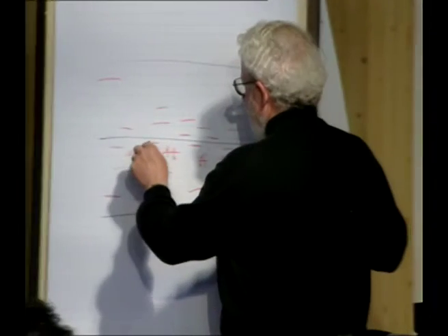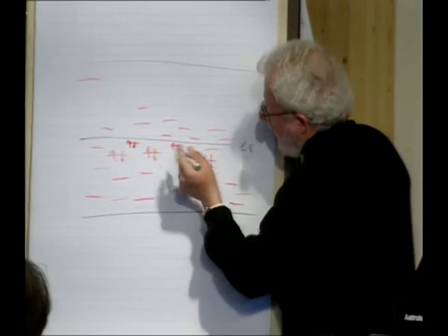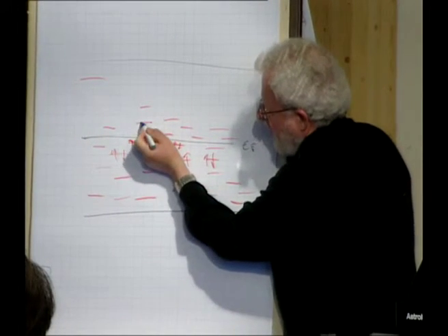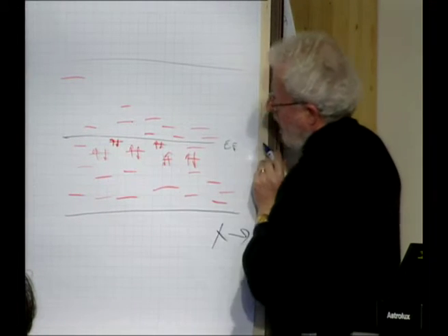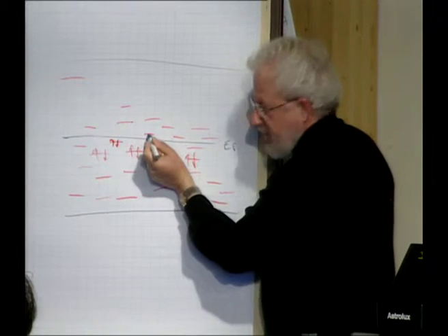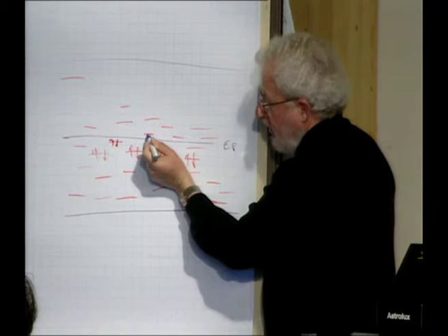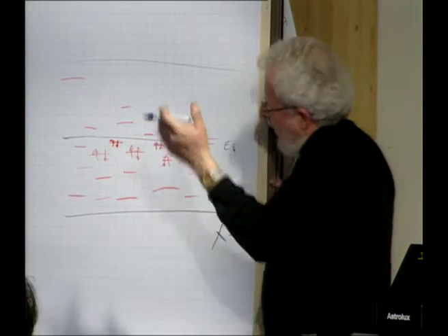So now I go to a finite temperature, and Mott observed, if you go to a finite temperature, of course, Mott says, well, look, I can do thermal activation up to here. I can do thermal activation, but I can access this state more easily. It's a smaller activation energy, but it's farther away.